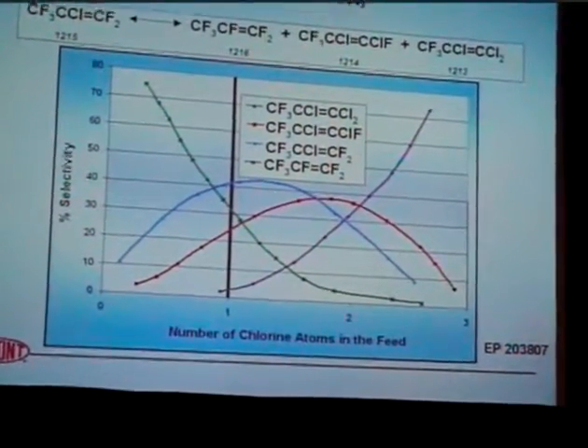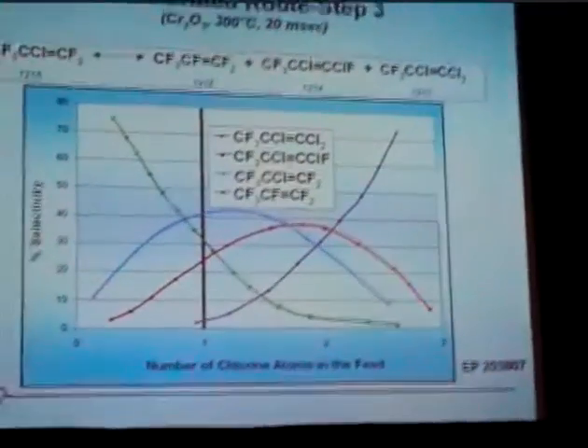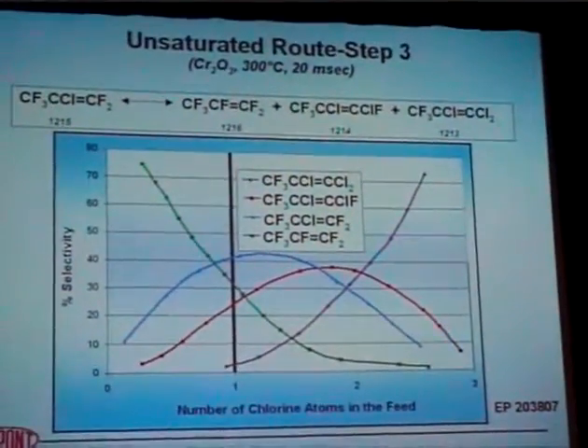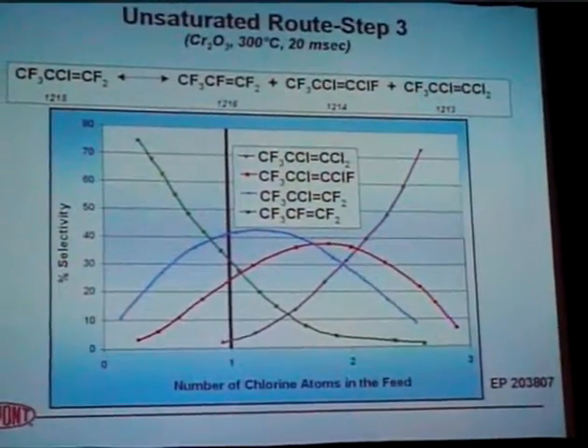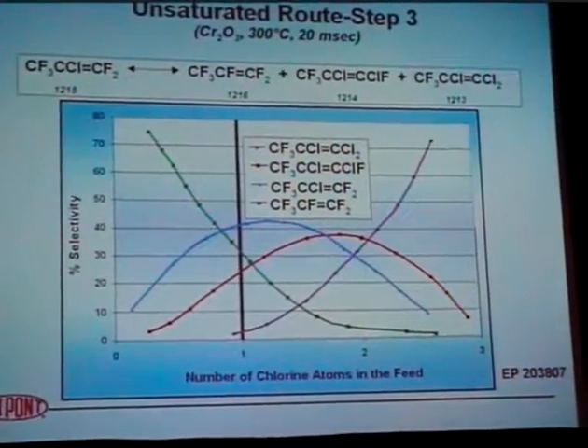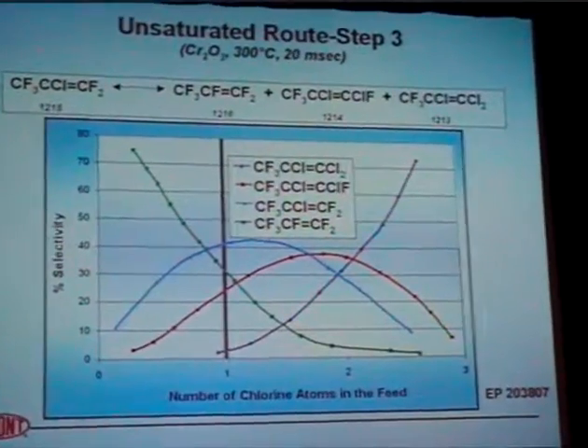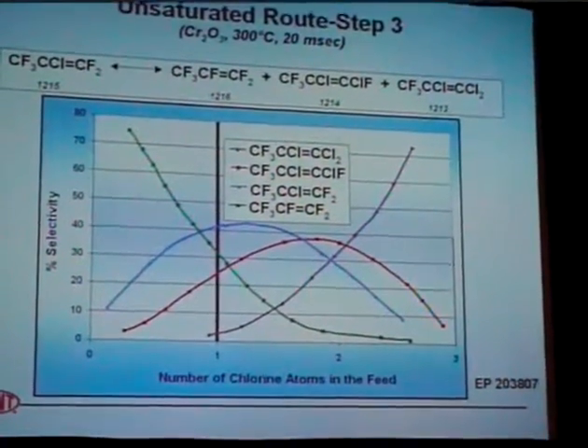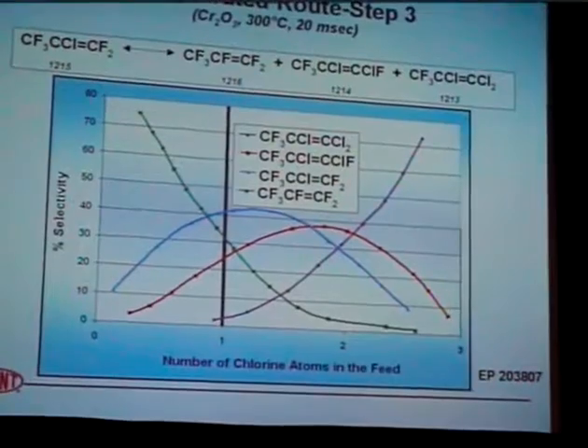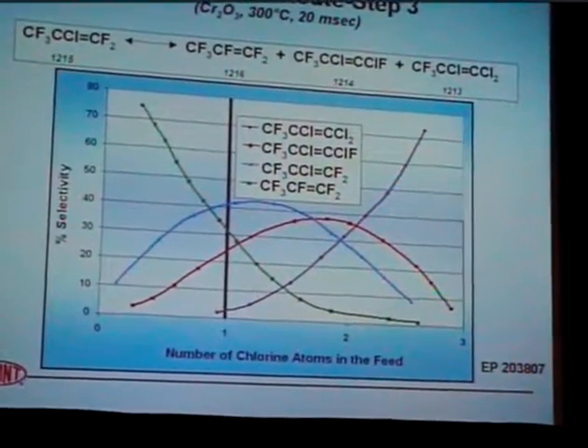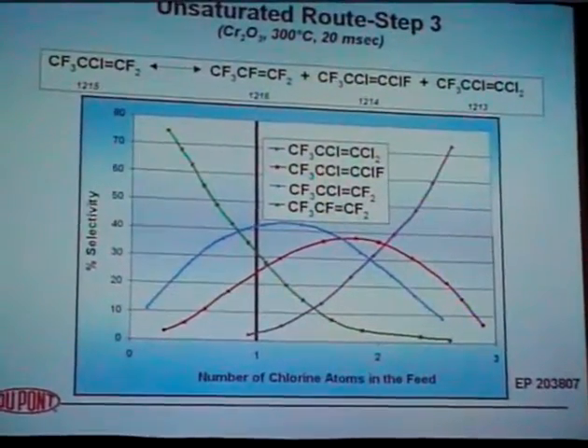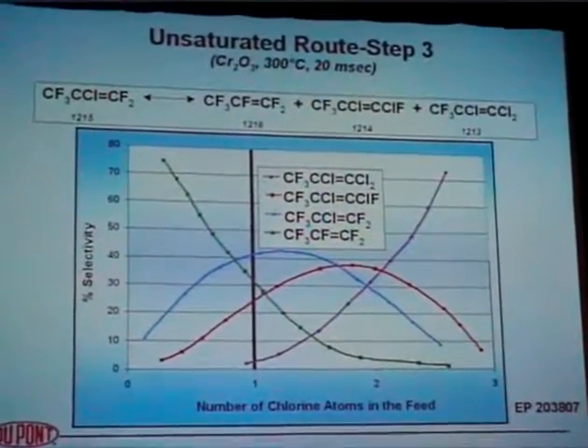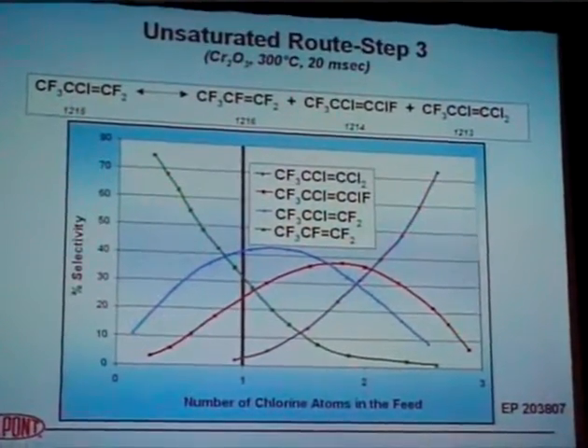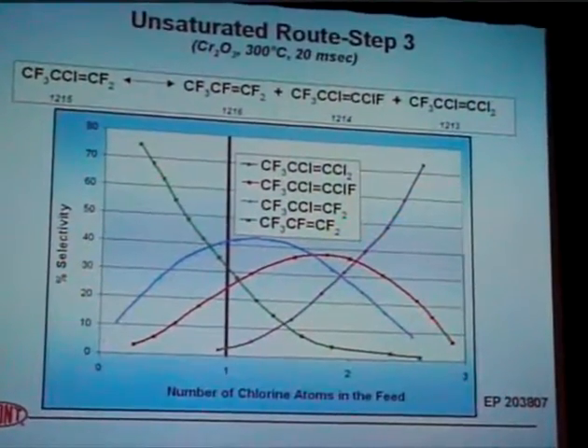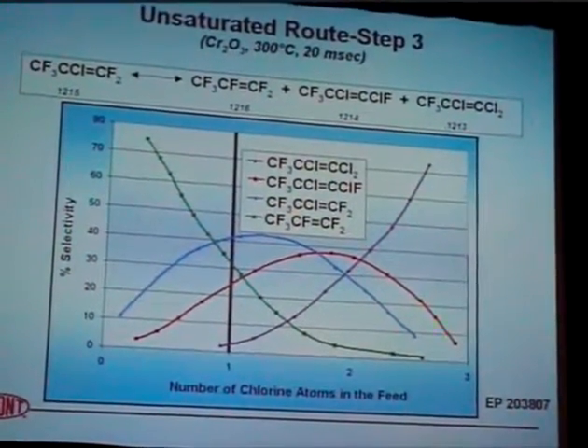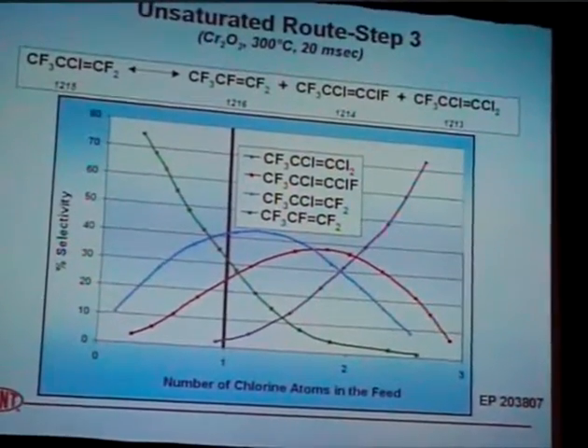So it's very important in this distribution of products that you get out that you isolate the less fluorinated materials, the 12-14 and 12-13. Do not recycle them in this reaction, but take them back to the previous reactor, react it with HF, and build out the fluorines on the molecule so that you feed relatively pure 12-15 to this reaction. Otherwise, the concentration of hexafluoropropylene drops way off. So I like this reaction. I think it's very, very nifty catalysis, the fact that you can keep the double bond in there all the way through the process.